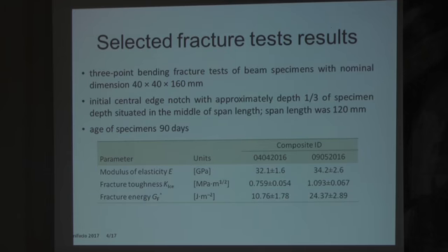As I said, these specimens underwent the fracture test. It was a fracture test in 3-point bending configuration, and the tests were under displacement-controlled loading. That means we could record the load-deflection diagram of these experiments, and these diagrams were evaluated. From the first almost linear part of this diagram, we estimated the value of the modulus of elasticity, then using the effective crack approach we determined the effective fracture toughness, and using the work of fracture we determined the fracture energy. In the table you can see the values of these parameters, the mean values and standard deviation of 6 specimens for each mixture.